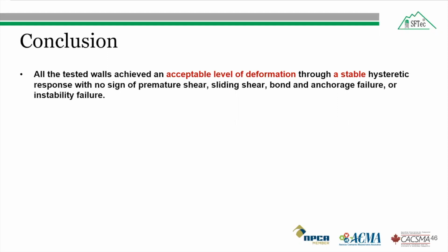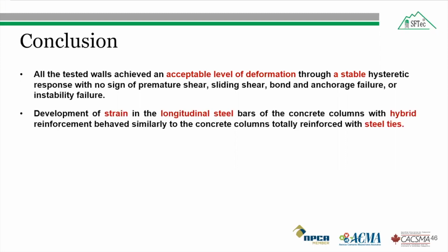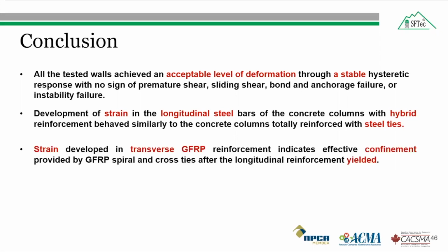In conclusion, the tested walls, irrespective of their aspect ratio, achieved an acceptable level of deformation through a stable response with no sign of premature failure. The strain developed in longitudinal steel bar showed that it was unaffected by the type of transverse reinforcement used, either steel or GFRP. The GFRP cross tie effectively confined the hybrid reinforced section after the yielding of longitudinal steel, and GFRP spiral became more effective in confining the column core after the concrete cover fell off.